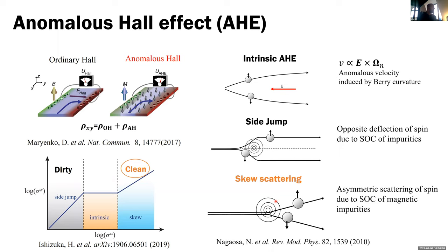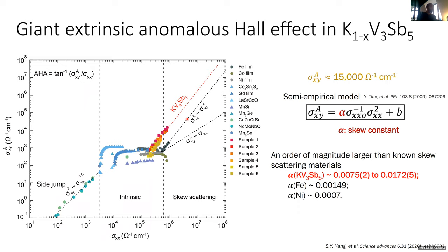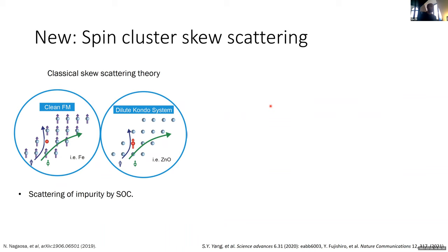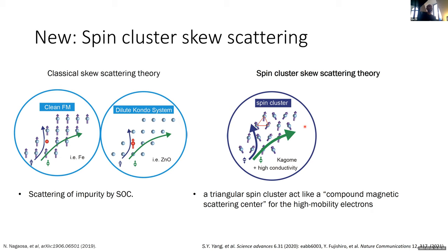But basically what we found is that KVSb showed a giant extrinsic anomalous Hall effect that overlapped into the skew scattering regime. And when I say giant, I mean it was very large, larger than iron with the similar scaling. The skew scattering constant, a metric to gauge how strong the effect is, so the level of exchange integral, is between a factor of 5 to an order of magnitude larger than iron, depending on sample. So it has a very large extrinsic anomalous Hall effect that came about due to the so-called spin cluster mechanism, which happened to be put forward by Nagaosa like 6 months before we discovered this.